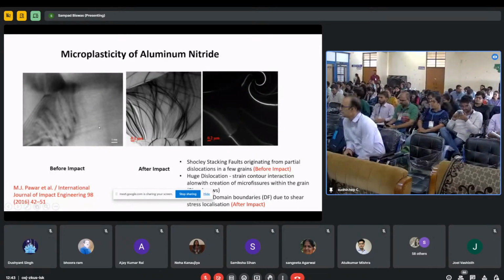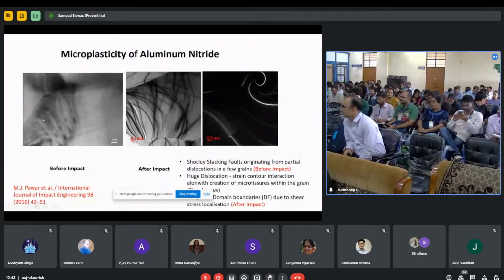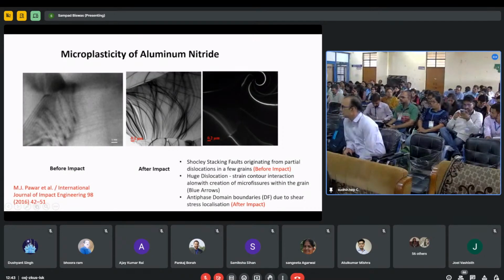So from that debris, we have taken this sample, the thin section. We have seen here the Shockley defects, and these Shockley stacking faults originated from the dislocations. You can see this is present in the original material. So the original material is also very important. It is present, but in very minor quantities. But when it is shocked, you can see lots of domain boundaries are also there. These are the antiphase domain boundaries, and these are caused due to local shear stresses. So it absorbs a lot of energy, and this is a dark field image. You can see clearly the domain boundaries. So this absorbs a lot of energy of the impacted bullet. So this happens in case of aluminum nitride, which is prone to ductility at a considerable confinement pressure.